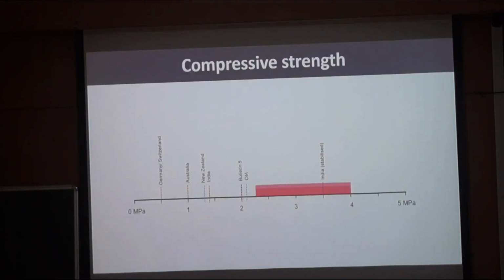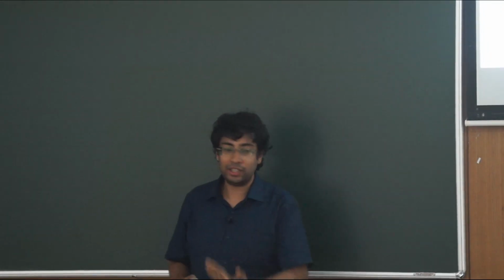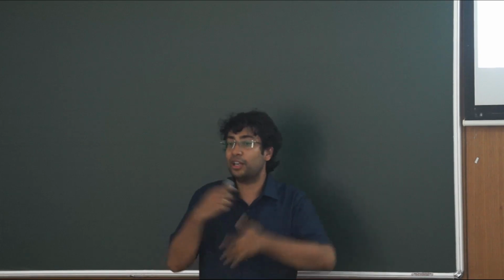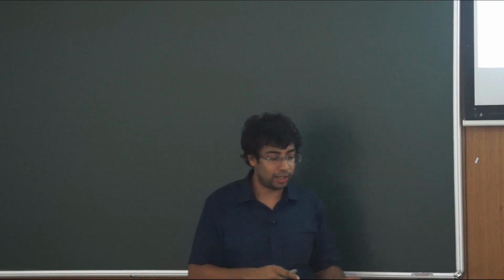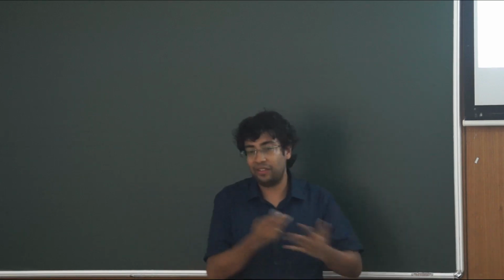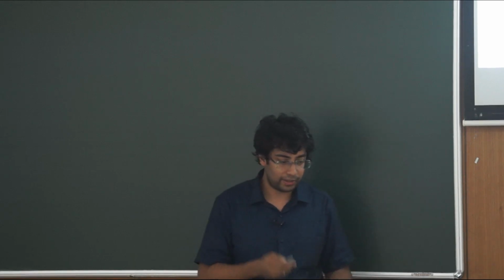I won't talk about compressive strength or strength today, because it's again a wider topic. Today I am going to talk about water resistance, which is more interesting. But just to give you an idea, here you see a range of strength, and what you see there is the building code requirement, or roughly 2 hours it starts disintegrating. So this clearly shows that cow dung improves the water resistance. And by doing the other test, which was the accelerated erosion test, we found it's 500 times. Different tests will give you different results, but it does improve water resistance.